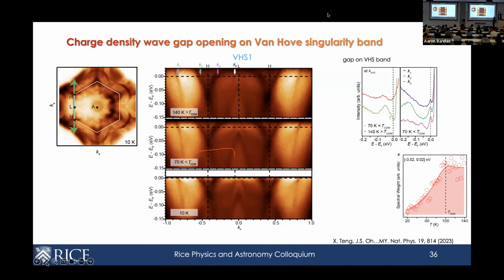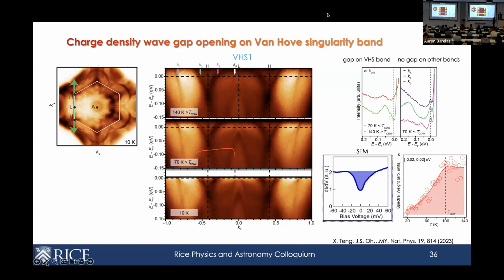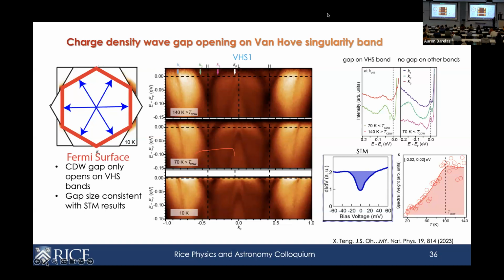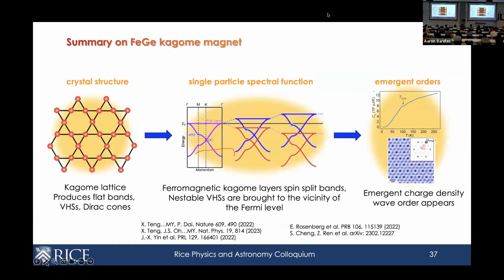suppression here. And this is indicating a gap that forms just like as seen in the STM data, right? And we can track the temperature at which this develops, and that is actually happening right at the CDW temperature. So therefore, we can actually see that the Van Hove singularity bands are indeed involved in the CDW order as expected. So here, in this example, I've shown you this information we have gained by looking and measuring the single particle spectral function. And from this, we can gain understanding that based on this crystal structure, this kind of band structure is actually roughly correct. And from this, we can see that this ferromagnetic Kagome layers spin split the bands, and therefore can actually actively bring the Van Hove singularities close enough to the Fermi level to eventually enable the formation of this emergent charge density wave order.